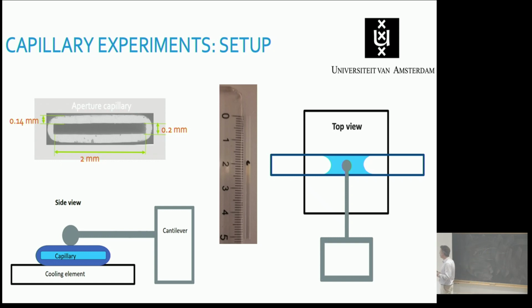So what do we do? We really want to do a controlled experiment in which we can see and measure everything. So instead of taking a complicated pore, we take a rectangular capillary that we partially fill with water, because the question was what happens if there's only partial saturation. And then we have a very simple cantilever measurement that looks at whether the glass expands or not when we freeze the water. Everything is on a Peltier, and we can look at it from the top, and we can see and measure everything.